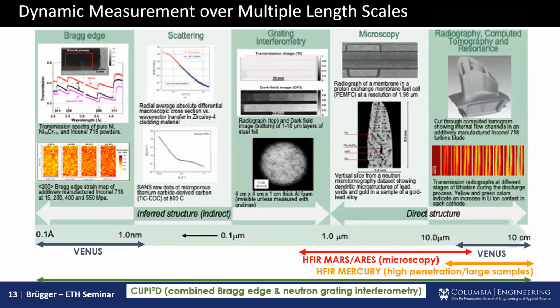So we can look at defects, and we can tune our gratings to detect defects such as porosity, for example, in material. So we can measure porosity throughout a material, spatially discriminated. And we can also measure, for example, nucleation of cracks before they form to be true cracks, which of course, if you're doing forensic engineering or optimization of 3D printed parts, is a huge upside. And then of course, on top of that, we can also do direct imaging, as one would normally do in a standard monochromatic beamline. So we can also overlay all of this information spatially, either in a 2D radiograph, or if we actually spin the sample in a 3D tomograph.